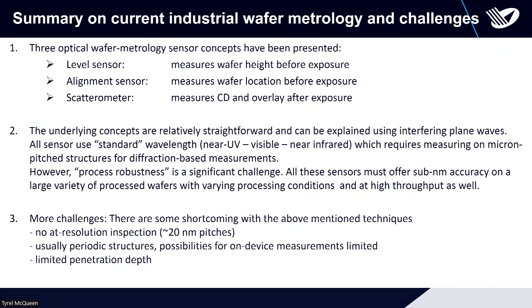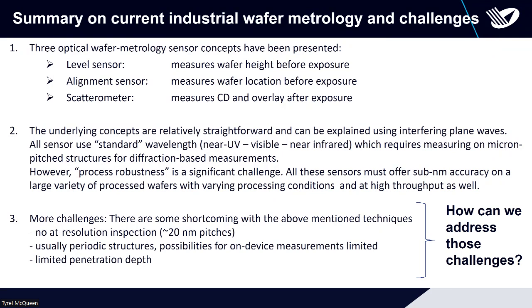Some of the challenges that are considered particularly important are listed here. With these techniques, there's almost no decent at-resolution inspection, with the exception of critical dimension scatterometry, but that's very model-based, so it's also not very direct. Of course, it would be nice to measure on something that is really fully representative of the device. At some point, an 8-micron grating is not very representative of a 10-nanometer device structure. We usually measure with periodic structures, but that is often not the case in an actual device. Only memory is really periodic. And all these wavelengths have very limited penetration depth, so they are not very well suited for 3D processes. So my challenge to you: how can we address that?